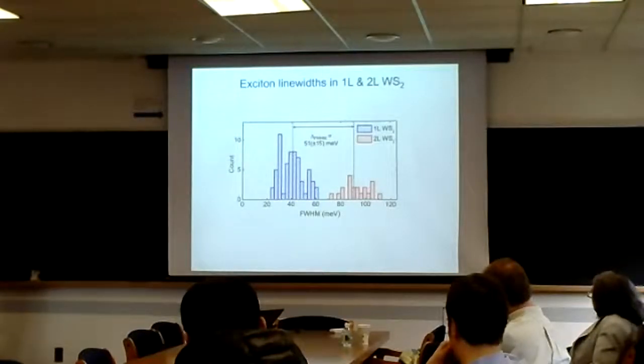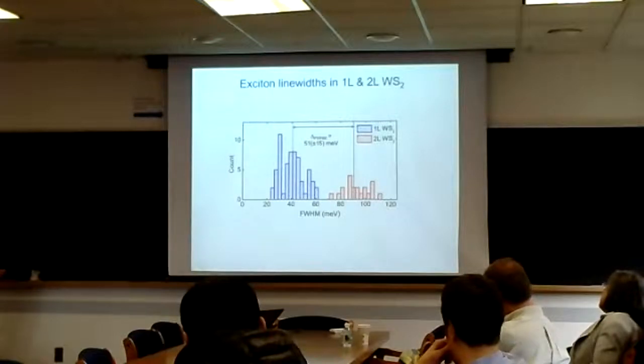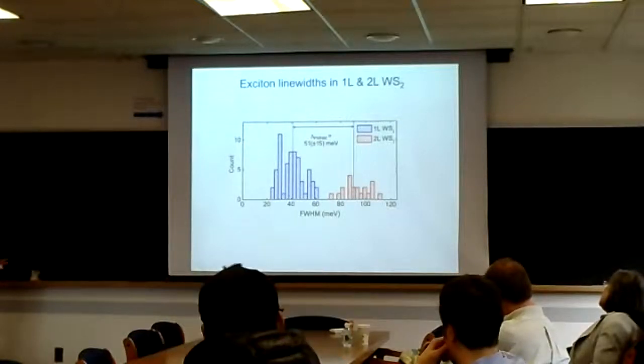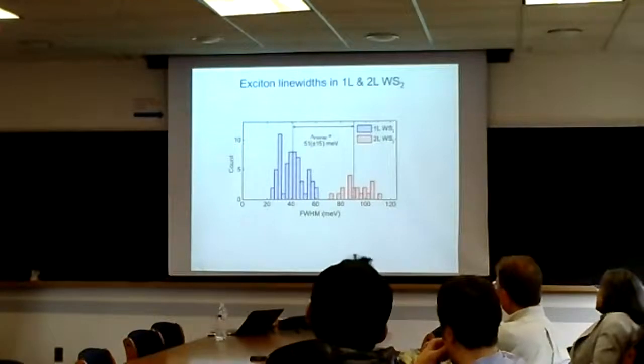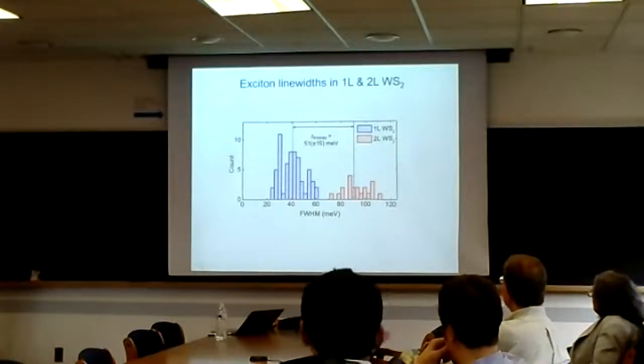During a PhD and a postdoc, you make many samples, and we looked at the line width statistics of many of these samples. We saw that there is a statistically significant difference of about 50 meV, which corresponds to processes on the order of 10 femtoseconds going on between this monolayer and the bilayer. And we wanted to understand this better.